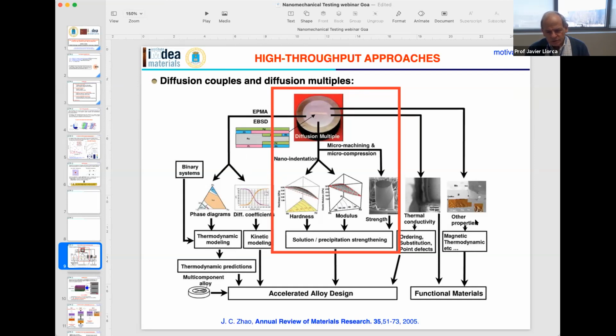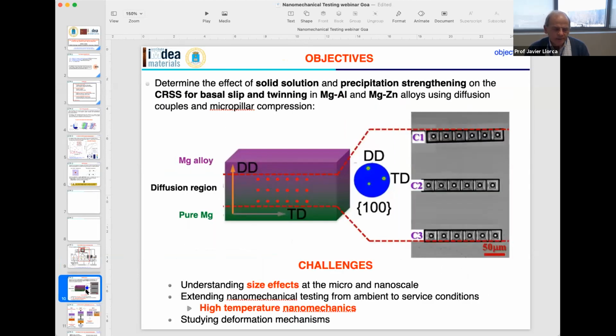They have also been used to study thermal conductivity and magnetic properties. But basically, diffusion couples in combination with micromechanical testing techniques like nanoindentation or micropillar compression allow a high throughput technique to measure the critical resolved shear stress of different deformation modes for materials with different composition. And these are the two techniques, diffusion couples in combination with micromechanical testing, that we have used in order to try to develop high throughput strategies to measure the critical resolved shear stress for different deformation modes in magnesium.